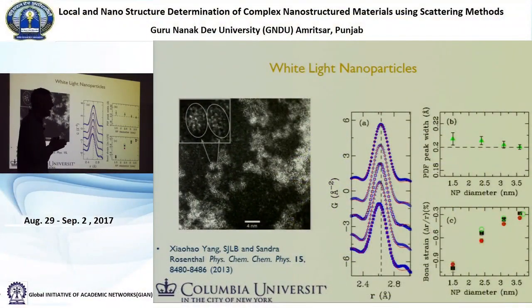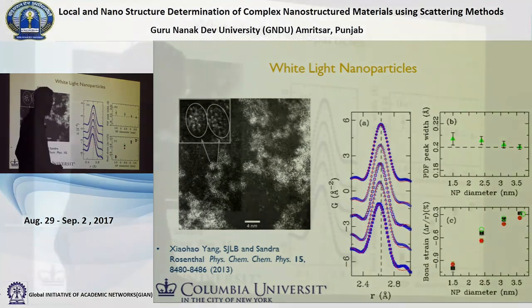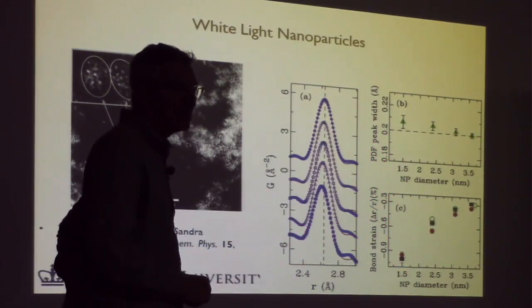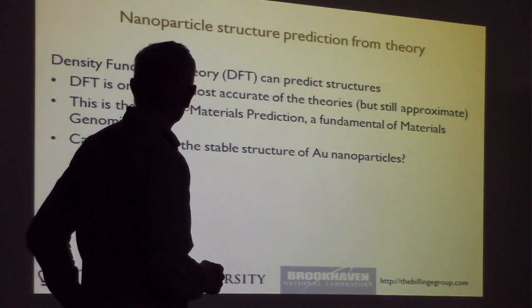And the reason is that some atoms are at the center of the nanoparticle and some of them are near the surface. And there's no reason why those two atoms that have different environments would have the same bond length. So some of them will be longer and some shorter. You don't actually know whether the long bonds are in the middle or the long bonds are on the surface. You don't have a good enough structural model to tell that. But just looking at this peak width here, it tells you that the inhomogeneous strain is increasing as the nanoparticle gets smaller.